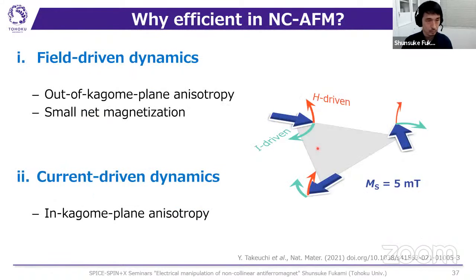So at the last part of my talk, I'd like to discuss why the spin torque on the non-collinear antiferromagnet is so efficient. Actually, we have not reached a solid conclusion, but we think that for the field-driven dynamics, the out-of-Kagome-plane anisotropy governs the threshold field or the coercive field, and also the small net magnetization results in a large anisotropy field, resulting in a large coercive field. But the current-driven dynamics is mainly governed by the in-Kagome-plane anisotropy, as shown here.